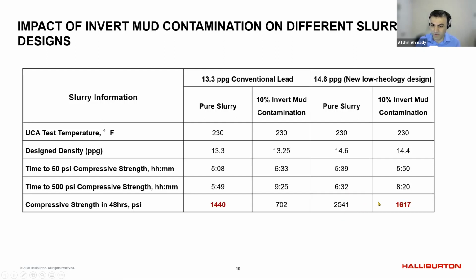2541 was the original one. Even with 10% contamination, it still is higher than original or pure slurry designed with 13.3. So the fact here is just having the higher density always is ideal to keep the cement property, and especially talking about the compressive strength and cement integrity over time.